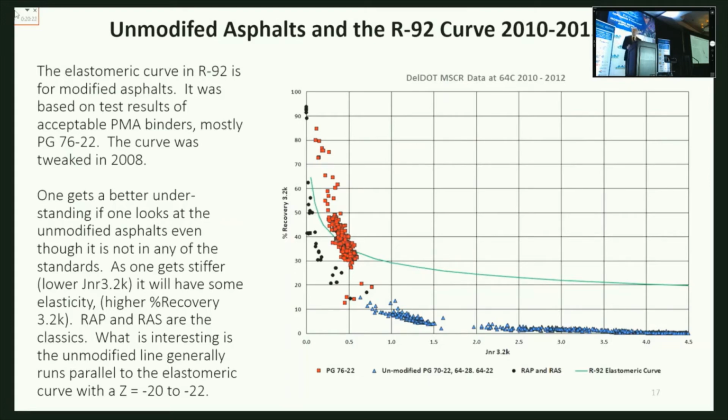We did not use the elastic recovery test because there are probably about 2 or 3 different versions in the Northeast on the temperature you ran it at. We just accepted it as polymer modified. So it was just straight AASHTO M320. Straight AASHTO M320. Okay. This is what you got from good old M320. They all met 76. Thank you for the question and clarification.